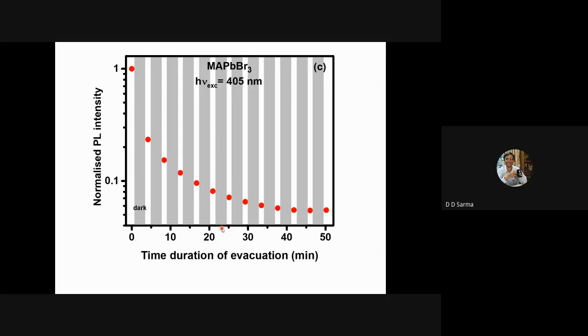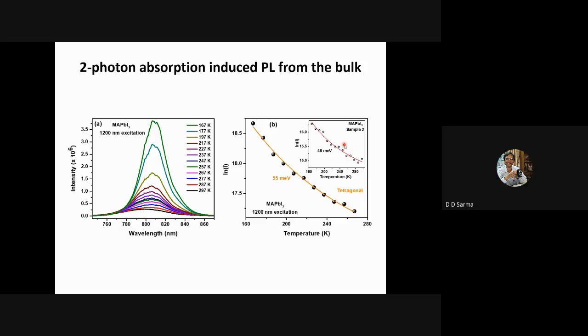But I'll provide many, many of these photons, such that there will be small probability events happening throughout the sample where two photons will combine simultaneously and give rise to an absorption, because two photons will have enough energy to excite the electron. And then this absorption is taking place deep inside the sample, throughout the sample, and the photoluminescence will take place deep inside, and it is not going to be sensitive to the surface defects. And then I can pump down and nothing would happen. And that's the kind of experiment we did.